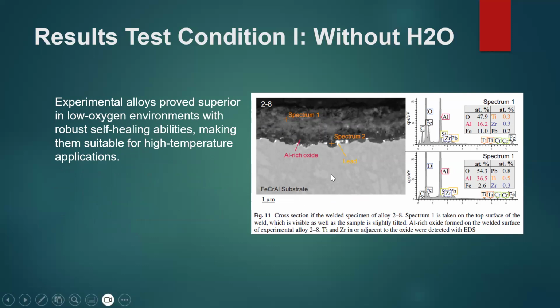This is figure 11, a cross-section of the weld specimen. Spectrum 1 is taken on the top surface of the weld, which is visible. The sample is slightly tilted, and aluminum-rich oxide is also formed on the weld surface of experimental alloy 2-8.